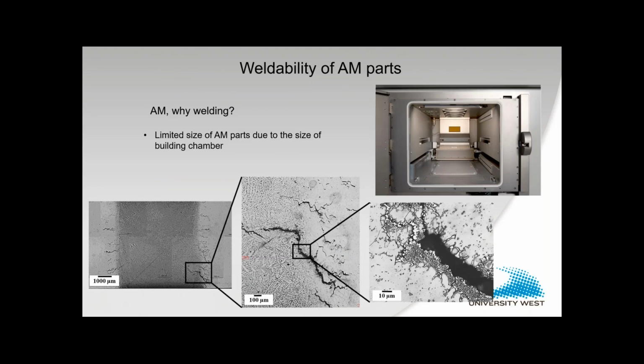But then another concept plays in, and that is that every material form, like forgings or castings, for instance, has its inherent history and susceptibility to cracking, for instance. And AM is also a new type of material form. So if we consider the size of the production chamber for powder bed fusion, we can realize that the chambers are quite small, and we need to actually utilize welding to produce these larger components. So welding of AM produced parts is extremely important, and that's an area which has not been really fully explored.